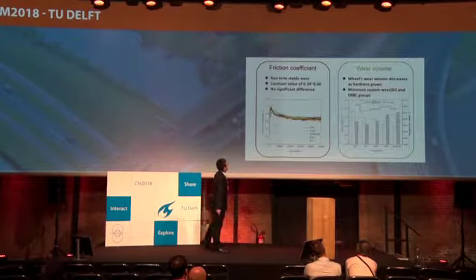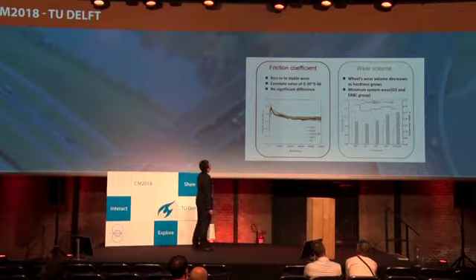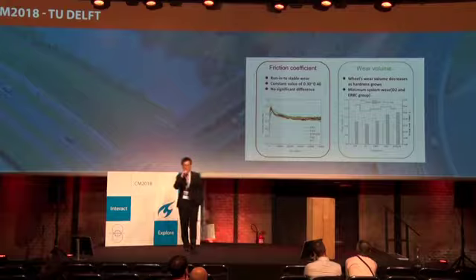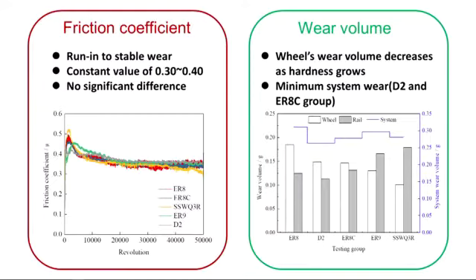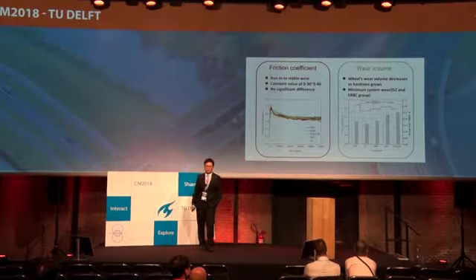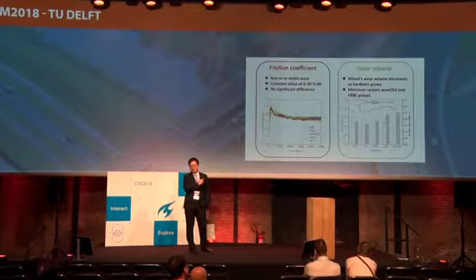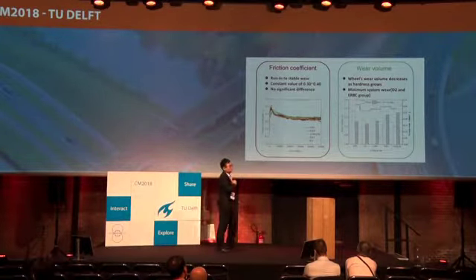Sorry. So here are some results of the testing. First, I want to talk about the friction coefficient, because when you use different kinds of materials, it's very important to make sure that your friction conditions are the same. And all these 5 groups of testing specimens show the same changing tendency of the friction coefficient. It stays almost in the same range, a constant value of 0.3 to 0.4, and there is no significant difference between the 5 groups. So, under the same friction conditions, we can say the comparison of these materials' performance is reasonable.